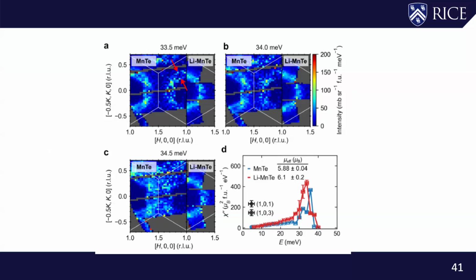What this actually means is that if you really try to think about altermagnetism and understand the transport properties, you cannot conclusively think about the system as being only local or only itinerant. You really have to think about the system in terms of magnetism. You can more or less think about it as a local moment, but in order to introduce itinerancy into the system, the magnets have to be interacting with itinerant electrons. And therefore, the system is actually much more complicated than the naive notion that you just have an altermagnet, and it will give rise to an anomalous Hall effect.